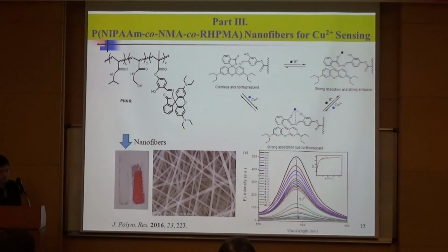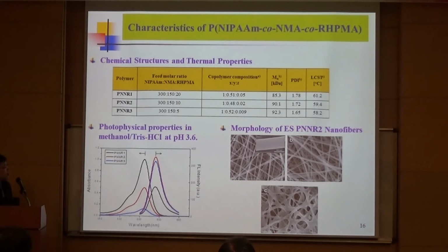of copper ions. So in order to build up an on-off type sensor, we first activate the absorption and fluorescence in acidic condition and then quench the fluorescence by addition of copper ion. And this fluorescence quenching will be quantitatively analyzed. Here we also synthesize 3 different polymers with different compositions. This table shows their chemical structures and thermal properties.